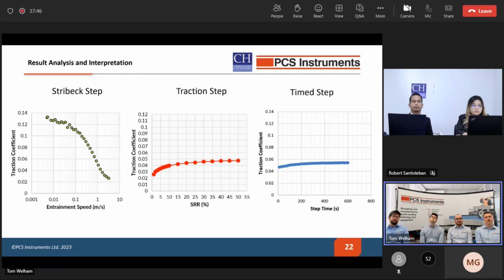A Stribeck step is where we look at how entrainment speed affects traction or friction for a fixed slide roll ratio. So we change the speed and keep the slide roll ratio constant. A traction step is where we fix the entrainment speed and then see how the slide roll ratio affects the traction. And then finally a time step, where we look at the evolution of the traction coefficient over time, while we either ramp or keep the speed and slide roll ratio constant.